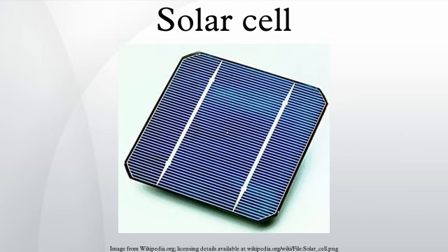In 2011, MIT and Michigan State researchers developed solar cells with a power efficiency close to 2% with a transparency to the human eye greater than 65%, achieved by selectively absorbing the ultraviolet and near-infrared parts of the spectrum with small molecule compounds. Researchers at UCLA more recently developed an analogous polymer solar cell, following the same approach, that is 70% transparent and has a 4% power conversion efficiency. These lightweight, flexible cells can be produced in bulk at a low cost and could be used to create power-generating windows. In 2013, researchers announced polymer cells with some 3% efficiency.